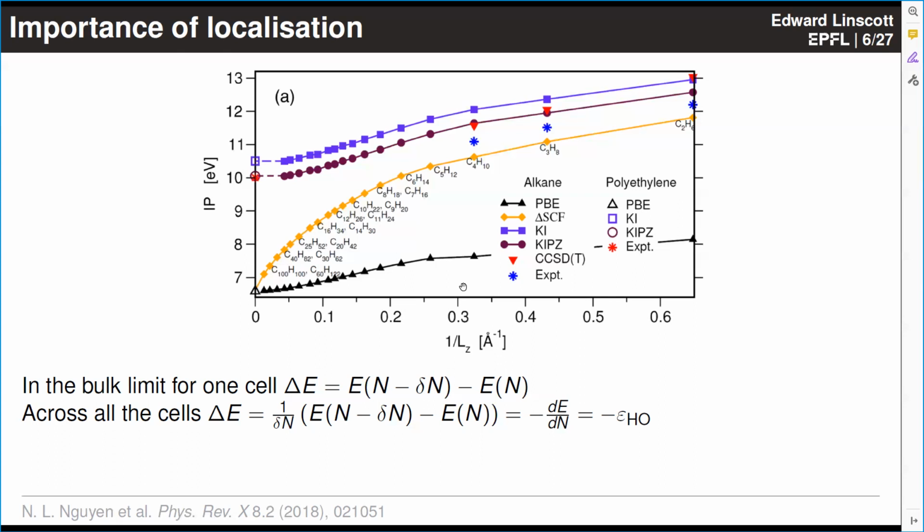The motivation to use Koopmans is that the idea of the band gap is much more well-founded in the Koopmans construction. Here we really have meaningful eigenvalues. DFT plus U is a sort of correction to total energies that happens to have the right effect of opening up the band gap, but I don't think there's any fundamental reason why DFT plus U should guarantee good band gaps. Whereas here we are explicitly targeting this property, so you can expect a better band gap.